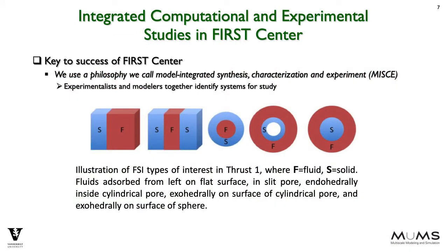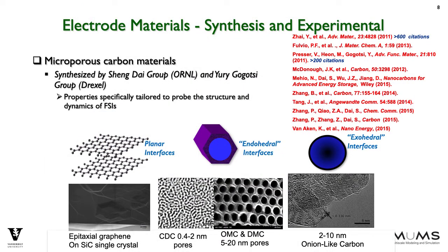One of the keys to success in the first center has been the way in which computational and experimental researchers have agreed to work on systems that are amenable to modeling. This means in some cases simplifying the geometries of the electrode-electrolyte systems into the kinds of simplified geometries that are shown in this figure here. And so our experimental colleagues have synthesized electrode materials that mimic these simplified geometries, including carbide-derived carbons, which have well-characterized pores, synthesized at Drexel, ordered mesoporous carbons, OMCs, and disordered mesoporous carbons, DMCs, synthesized at Oak Ridge National Lab, and onion-like carbons, synthesized at Drexel.